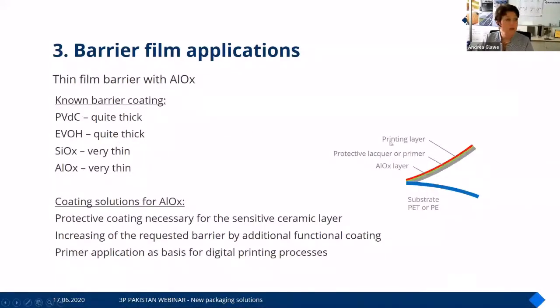Huge trend, I already mentioned that, aluminium oxide. Aluminium oxide for sure is not realized with our machines. Here are companies like Bühler or Applied Materials or others which are doing that aluminium oxide layer in a vacuum way. But the next step is necessary to protect that sensitive ceramic layer with an additional coating. It's also necessary to apply an additional barrier in order to get a much better performance. And also for digital printing processes, it's necessary to protect that ceramic layer in addition.